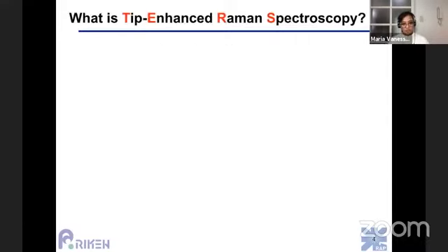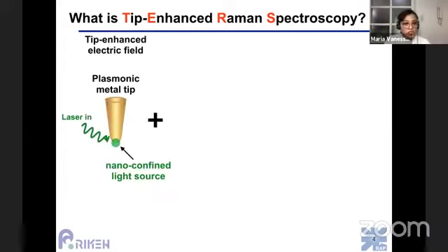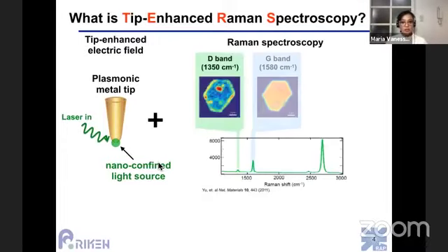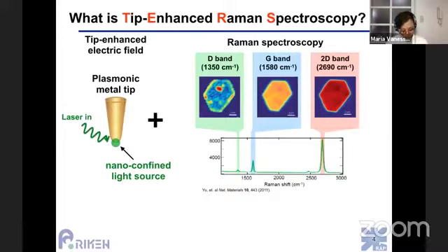Now, going to the meat of the presentation, I mentioned we are using a technique called near-field scanning optical microscopy. It's a big family, and one particular member of this family I'm using is Tip-Enhanced Raman spectroscopy. For those of you who are not familiar, Tip-Enhanced Raman spectroscopy combines a plasmonic metal tip, wherein when you shine laser light on that tip, a nano-confined light source is generated at the tip end due to photon confinement and leads to a tip-enhanced electric field. And combining this tip with Raman spectroscopy, which is a very powerful technique to distinguish the chemical properties of a sample, if you image each single peak from the Raman spectrum, you can actually get various